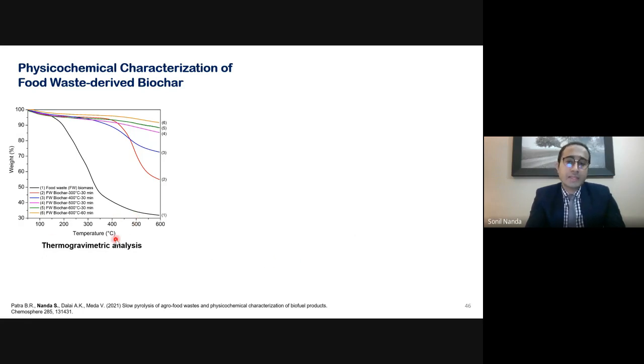Now, thermogravimetric analysis is an analysis that determines the thermal stability of a solid fuel. So it also determines the devolatilization behavior. What you could see here is the food waste, which is shown in the black color here. It shows maximum weight loss at 600 degrees Celsius because it's untreated, and it contains a wide variety of different volatile matter, and it contains a lot of moisture content because it's food waste. And then the biochar which were produced, we can see here the biochar produced at 300, 400, and 500 degrees Celsius, as well as 600 degrees Celsius for 30 minutes and 60 minutes.